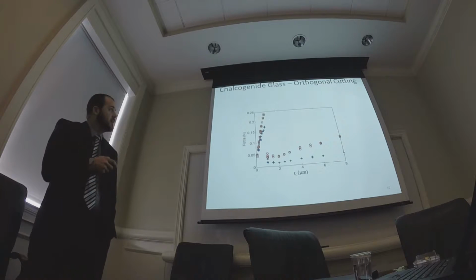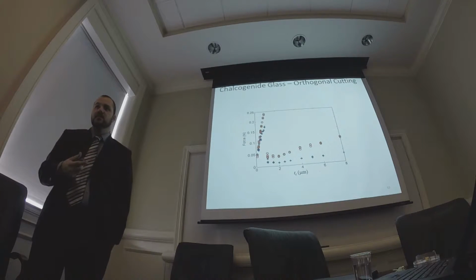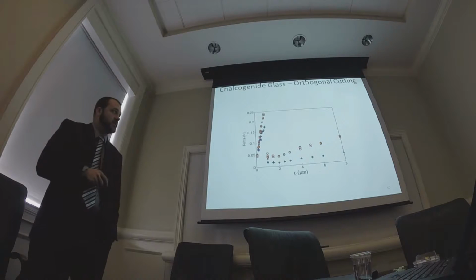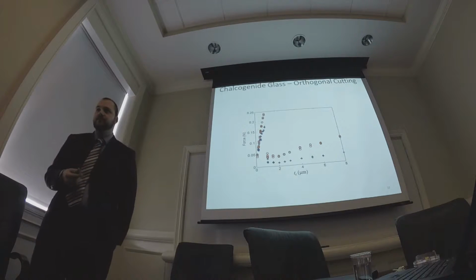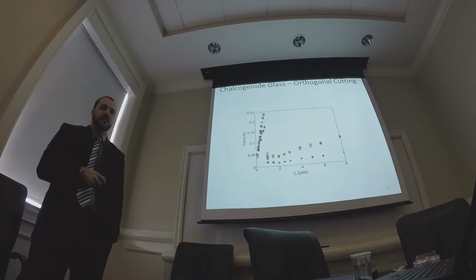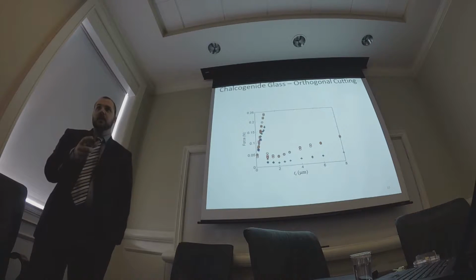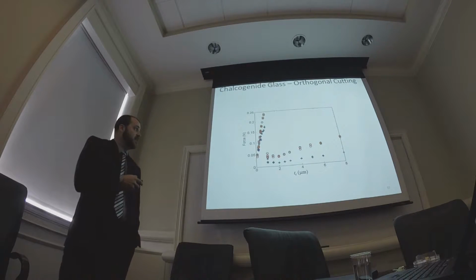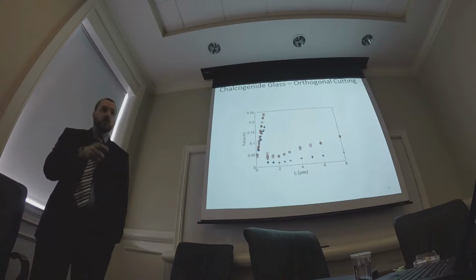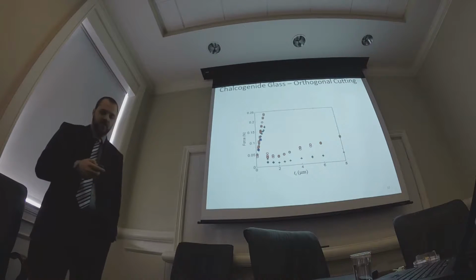The thing I want to point out is when we go from this test to this test, it doesn't happen instantly. There's a transient force that occurs. All these data points are steady state - I took an average of an entire 80 revolution test, and that point is the average of that test. If there was any big jumps throughout the test, I threw away that test and kept repeating it until I got 3 consecutive steady state forces, and that's where these points come from.